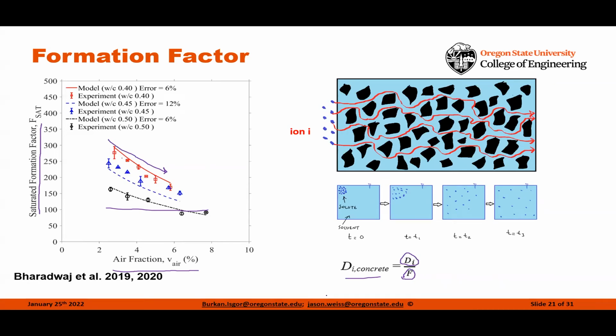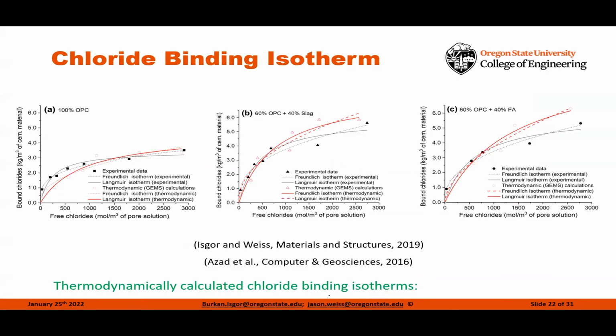When we start to do this, a lot of people say, well, what about the binding of the ions in the overall system? Well, what we're able to also do is use the thermodynamic model. And what's shown here in red are the thermodynamic predictions of modeling the binding of chloride ions in these systems compared to the black, which is the experimentally measured systems. And what we can see is there's a really strong correlation between simply taking the reacted microstructures and starting to calculate binding and doing the experimental measurements.